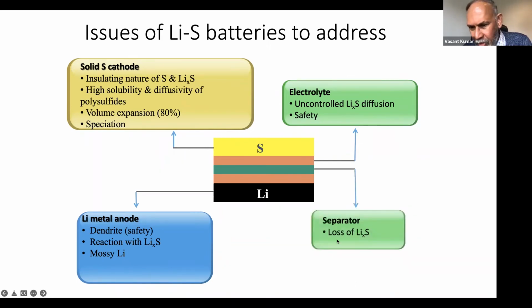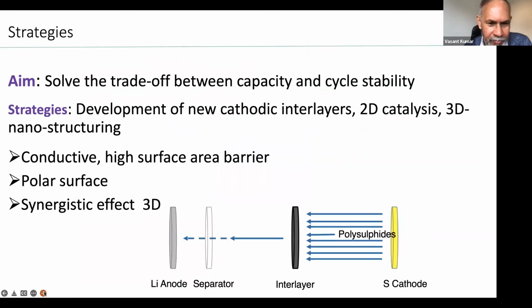And at the separator there is a large loss of lithium sulfide. There is an uncontrolled lithium sulfide diffusion and chemical gradient, and therefore it shuttles from one end to the other. To solve the problem, there are many approaches. One is the trade-off between the capacity and the cycle stability.